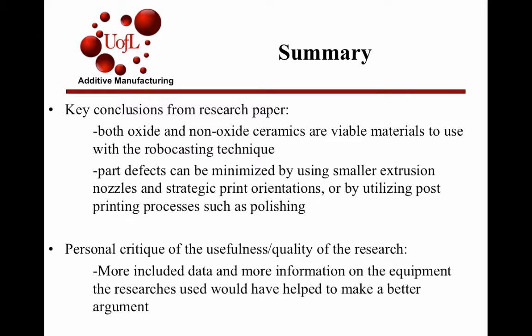So the conclusions are both oxide and non-oxide ceramics are viable materials to use with the robocasting technique. The defects can be minimized. The surface defects can be minimized by the small extrusion nozzle, strategic print orientation, or utilizing post-printing processes such as polishing or sanding or something of that nature.